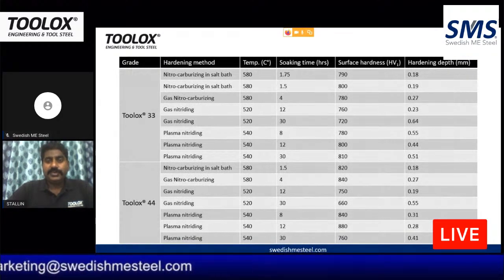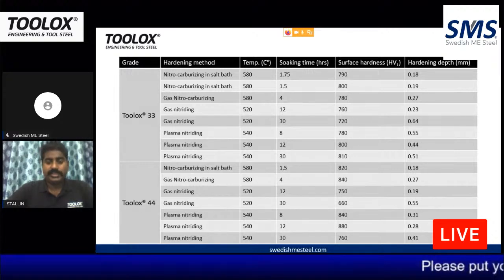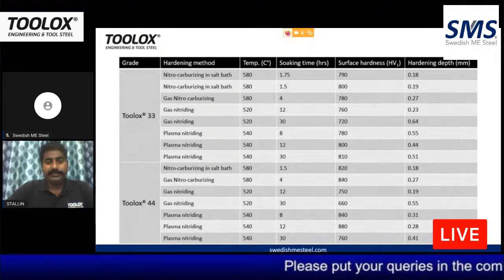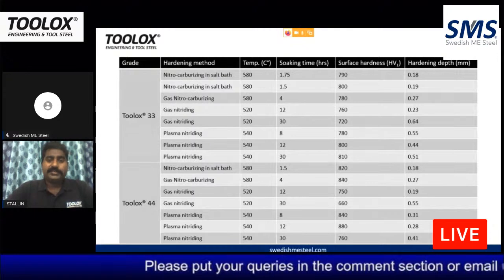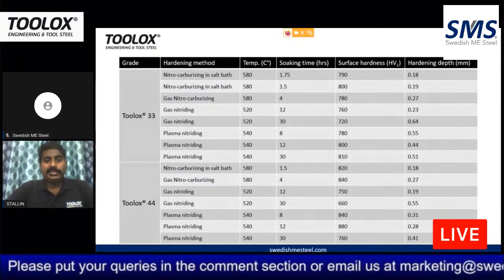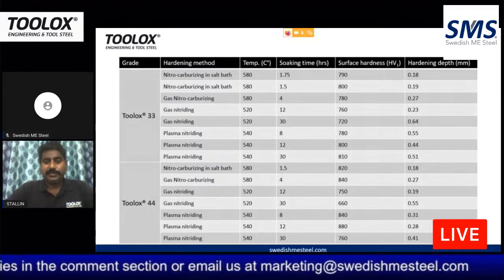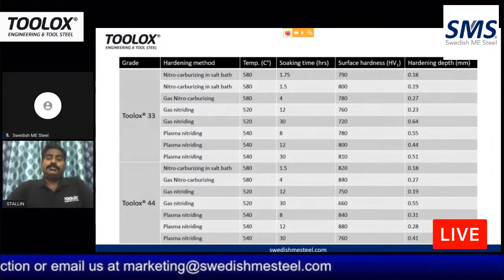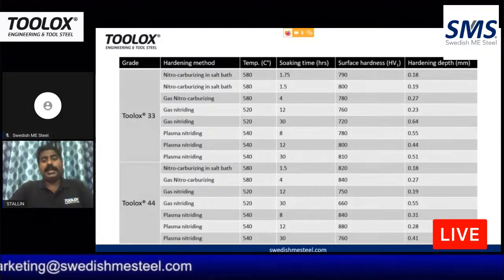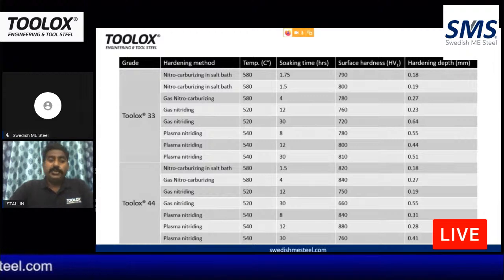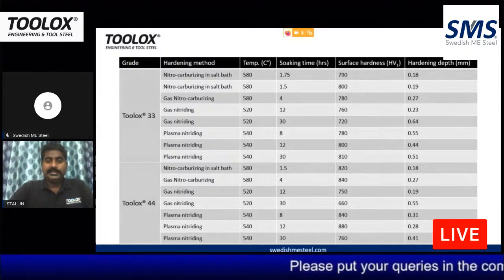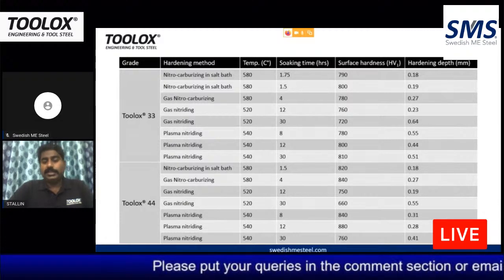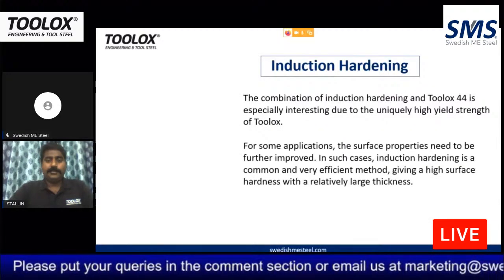This graph gives you a rough idea. We have posted this based on our own experience with the heat treatment. For both grades of Toolox, depending upon the soaking time and the temperature you maintain, and based on what kind of surface hardness and hardening depth you require, you can use these materials. And this graph would be very convenient for you to use whenever nitriding is being done.